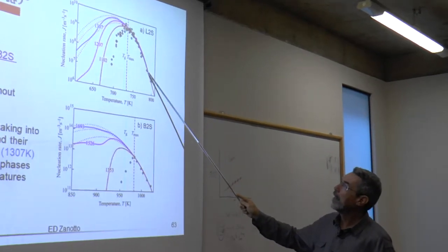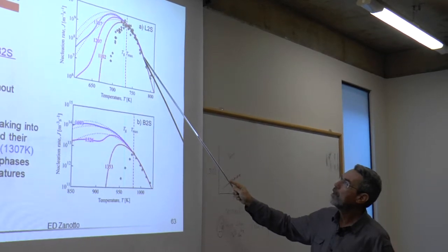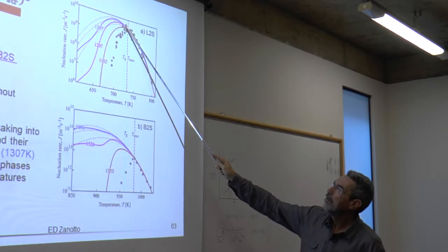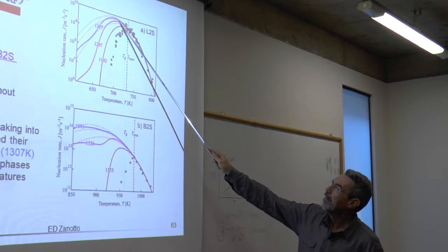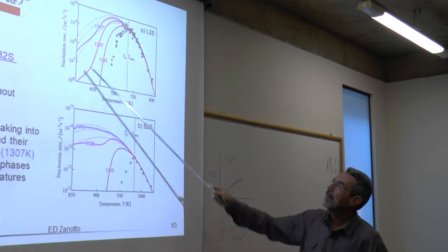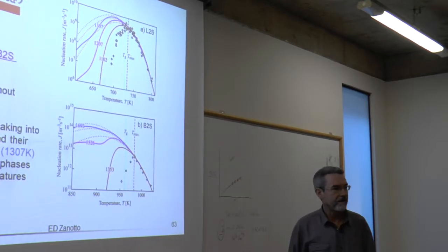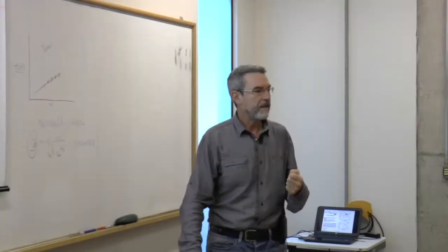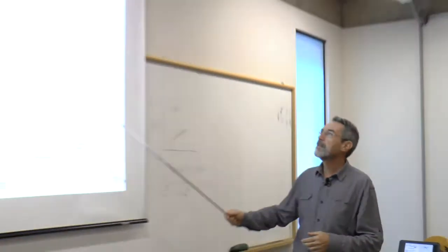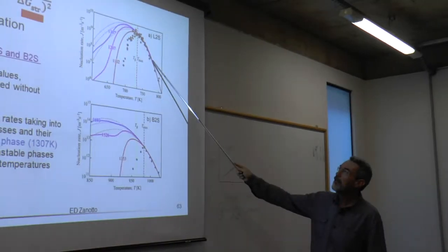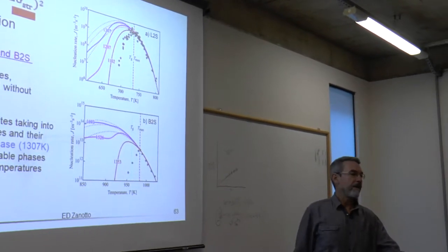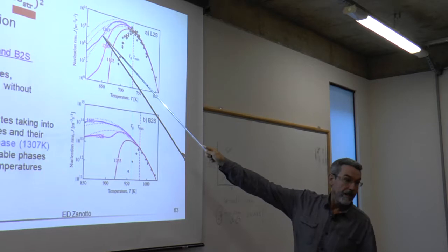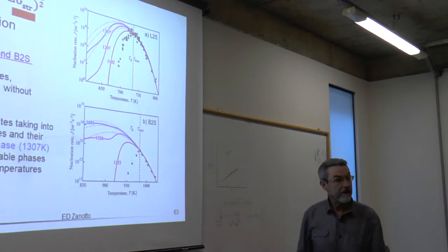And see the blue curve here. Now that blue curve comes here, coincides with the red curve, and goes all the way to here, but doesn't describe the nucleation rates. That's my point. Even taking the stresses into account, even taking into account the fact that they will somewhat relax, it doesn't change here because they relax very fast. It doesn't explain here. They don't relax so fast below Tg, but it doesn't explain.